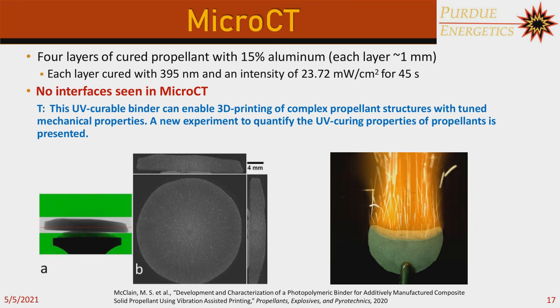Slide 17. Lastly, we looked at the microstructure of cured propellant. In this image in the bottom left, we cured 4 different layers. The point of this study was to see if there was any phase separation between the photopolymer and the particles, because in other studies I've seen that they use low viscosity photopolymers, which might separate from your energetic particles. Here we didn't really see that, which was promising. We also did a little bit of combustion on it, but the main takeaway from the study is that we now have a potential photopolymer that is tailorable that we can use to 3D print more complex propellant structures, and we have a way to quantify the cure depth, which is an important parameter for this type of printing.